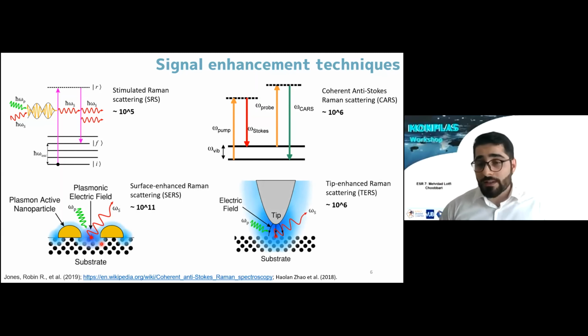And finally, we have tip enhanced Raman scattering here, or TERS, in which we use a plasmon active tip and we bring it into close proximity of the sample. And when we illuminate the light onto the tip's apex, the local surface plasmon resonance will happen on the tip's apex and to some extent onto the sample. And it can confine and enhance the light field and therefore enhance the Raman signal up to 10 to the power 6 in comparison to the conventional Raman signal.